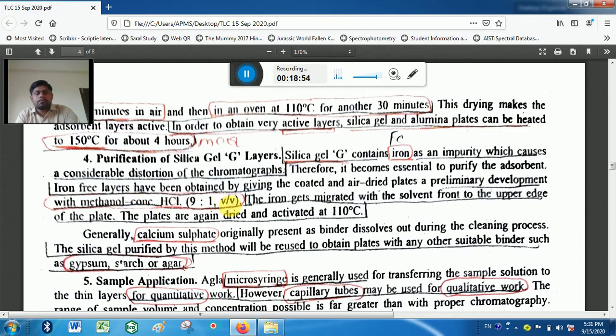That means here we prepare a methanol and concentrated HCl solution in a 9:1 ratio volume by volume. Then that solution is applied on that plate and then let it dry. In that manner, the iron that is present in an adsorbent layer is easily removed. The iron migrates with the solvent front to the upper edge. When you pass that methanol and concentrated HCl over the surface of the TLC plate, they remove the iron that is present in the adsorbent. Then the plates are dried and activated at 110 degrees Celsius.